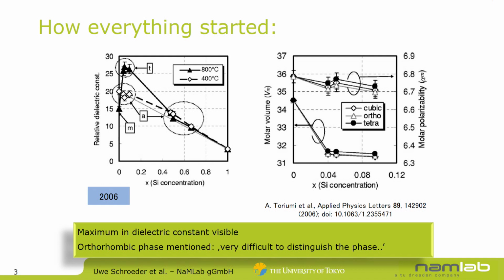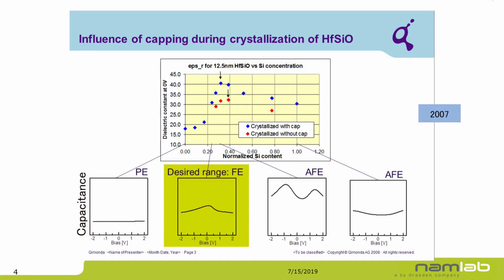And the first publication already mentioned that it's hard to distinguish the typical phases which you can get for the hafnium oxide: the cubic, the tetragonal, and the orthorhombic phase of the material. Okay, and this is the original slide from Qimonda at that time, which we showed our management. We basically copied the results from Tokyo. Here's the dielectric constant versus the silicon content in hafnium oxide.